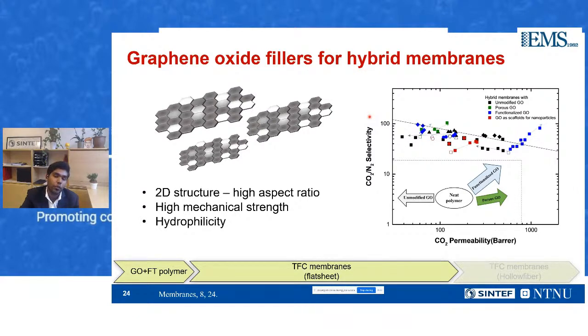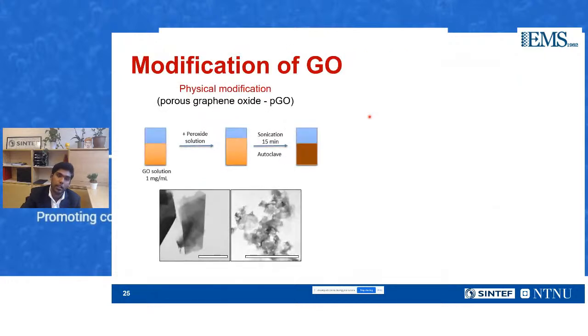But on the other side, if you make functionalized graphene oxide, or make holes in the graphene oxide, eventually making it porous, you have the possibility of increasing both CO2 permeability and selectivity. That's one of the reasons why we chose to modify the graphene oxide that we wanted to include in the system. So we chose two different modification procedures.